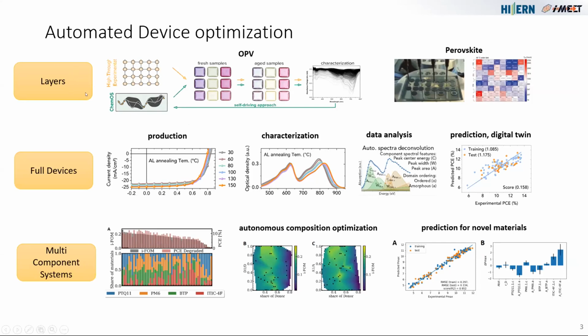We then continued our layer approach with Perovskites, where Yi Cheng has been heading all the activities, to basically make drop cast layers from perovskites like we had done for OPV, just in a different system. And then Yi Cheng tested a lot of different combinations of active layers for perovskites, again, for the stability, in this case, in particular thermal stability, but also light stability.